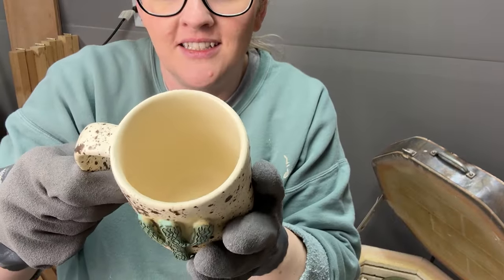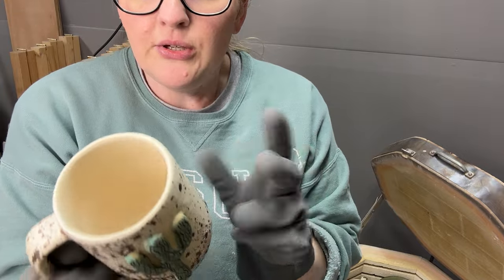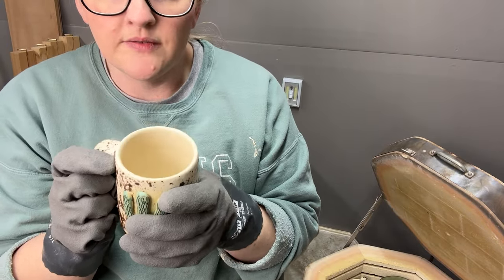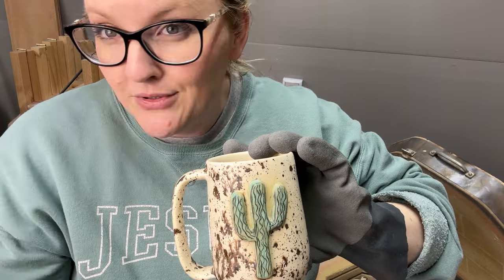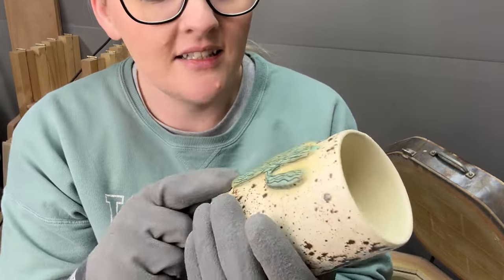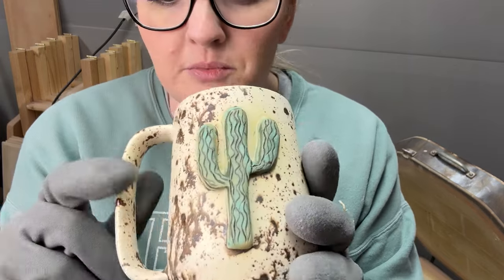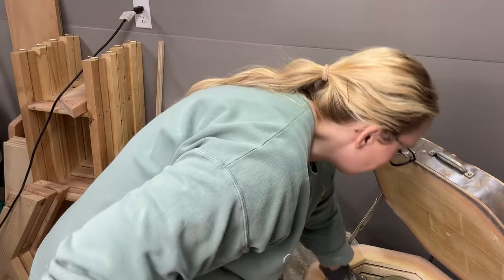I just love these so much. My winter wood was at the bottom of the jar, so it was really thick with the crystals. I had bought some alabaster because I wanted to do a couple coats of alabaster and then do the winter wood over top so that it wasn't so much. I also added a little bit of alabaster to the bottom of that winter wood jar and it helped to thin it out. I just love it. This is underglaze wiped back with satin patina, two light coats — you get the effect. I did two coats of alabaster inside and out, then one coat of winter wood, just dabbed on to get the crystals dispersed evenly. There are ten of those; only five in this firing, five more in the next.